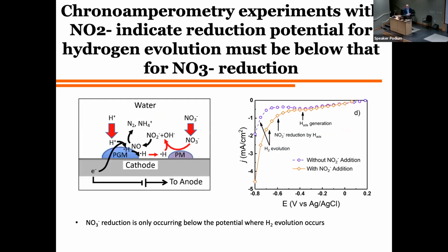And so we did something called chronoamperometry, where we took our reactor and we just stepped it through these different potentials. And we hold it at each potential for a little time to overcome the mass transfer limitations until the current stabilizes. And we get a profile like this.